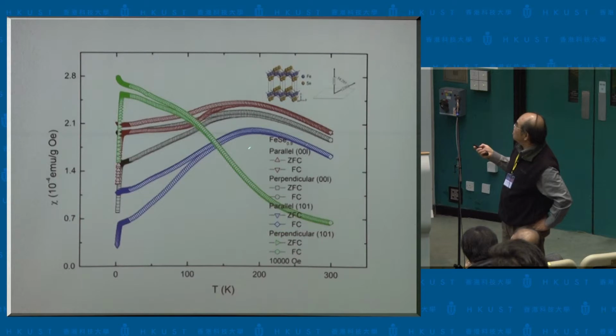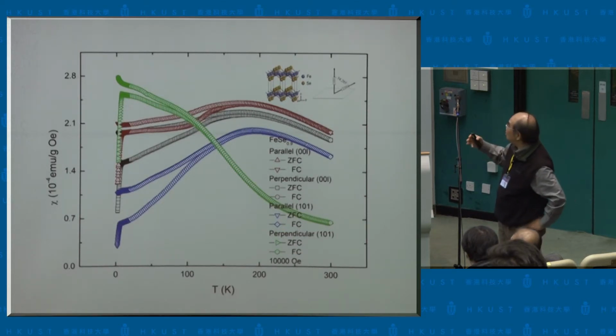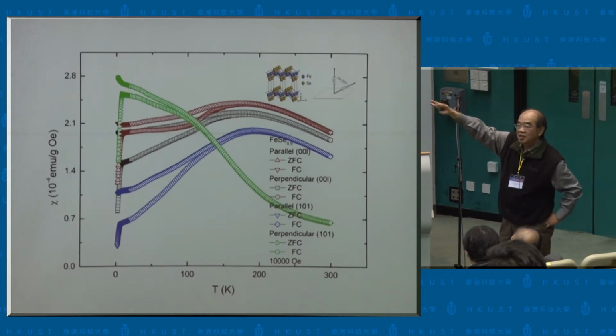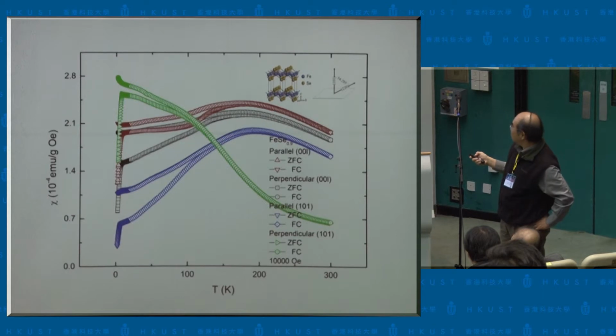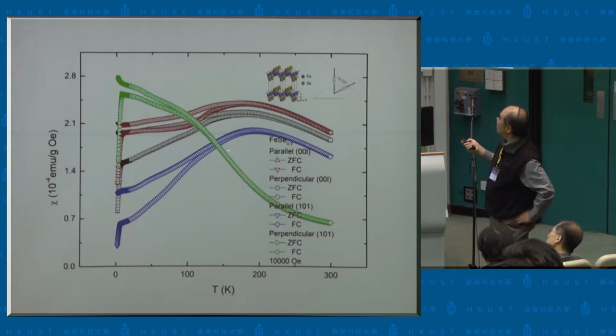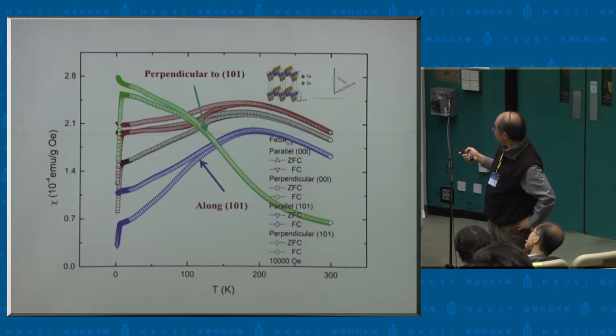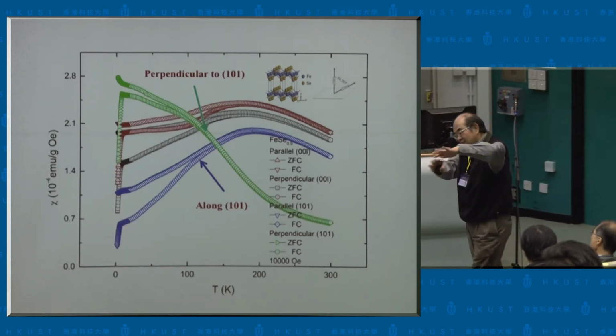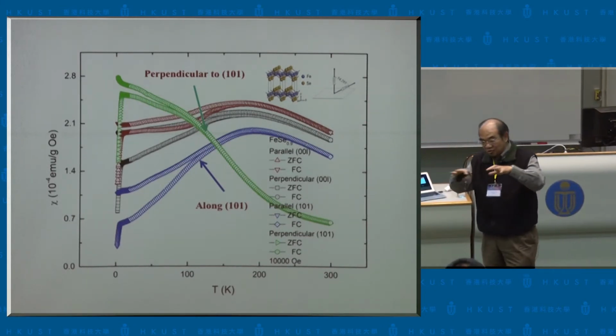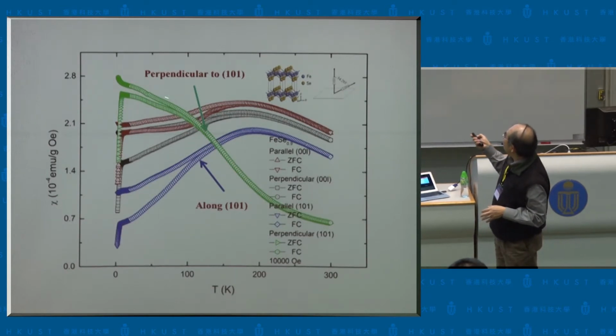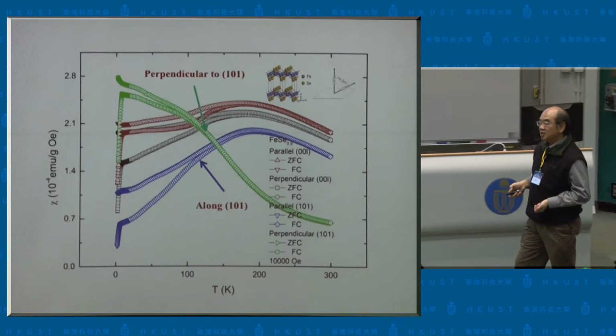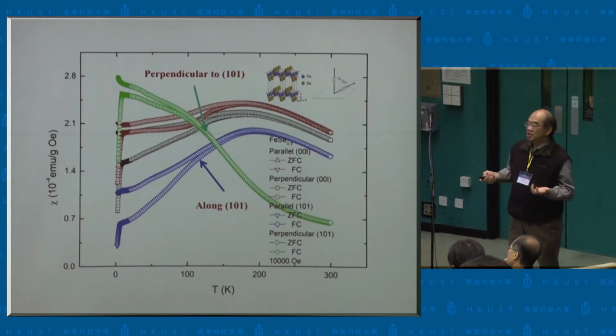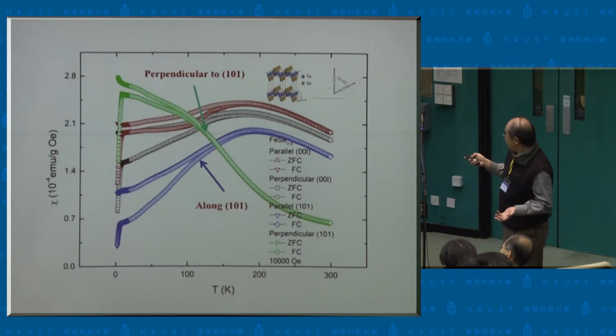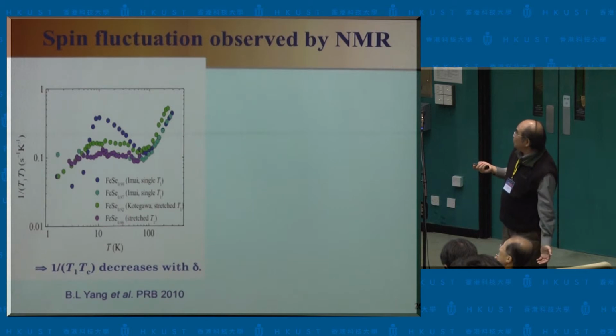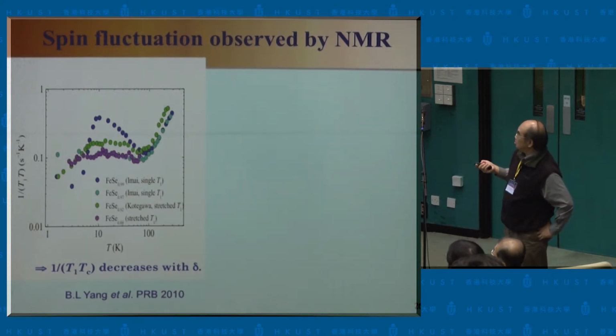That separation appears around 100, close to where there's a broad hump in the resistivity, as I showed you earlier, and it may also be closely related to the Hall effect. So there's a strong anisotropy along the 101 plane and perpendicular to 101. It means that this iron selenide seems more like itinerant, with mobile electrons, along one direction, and more localized along the perpendicular direction. That makes you think this has something to do with the orbital effect.